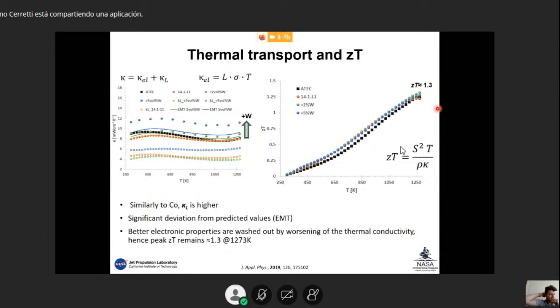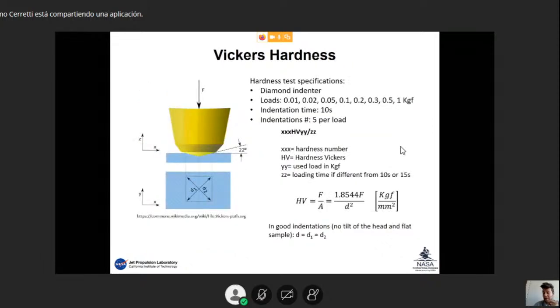But then, since these materials have a higher Young's modulus, and tungsten is an incredibly stiff material, we wanted to analyze some mechanical properties of the material. So we analyzed the hardness of the material. The Vickers hardness, the microhardness test, is what we used.